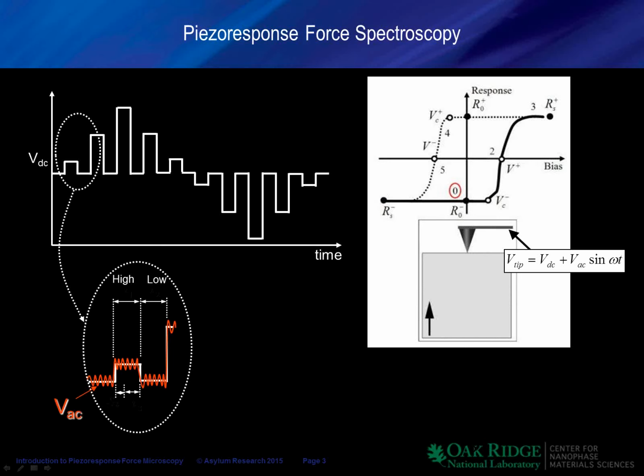So imagine that we put our AFM probe in contact with the surface and start to apply these rectangular pulses which are with increasing and then subsequently decreasing magnitude. So on top of these pulses, we are going to apply the sinusoidal waveform, sort of something that we normally do in the PFM. So let's see what's going to happen inside the material. Let's assume that in the beginning our sample is polarized in one direction. So in this case, we clearly have a saturated PFM signal.